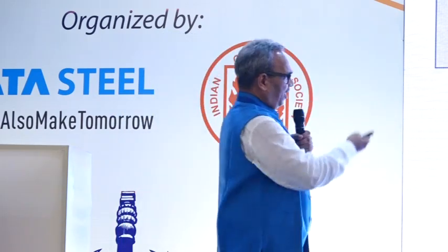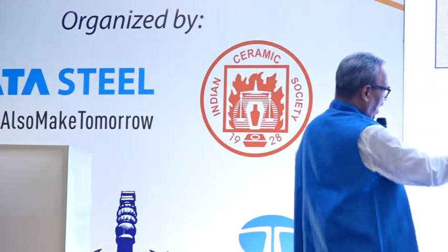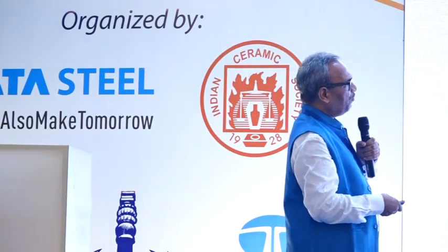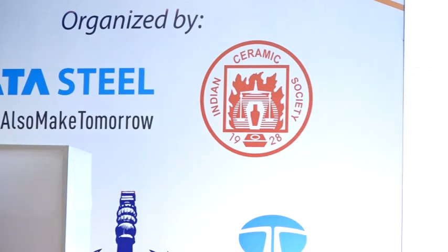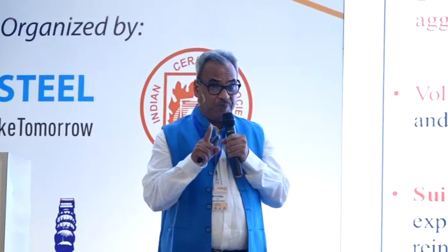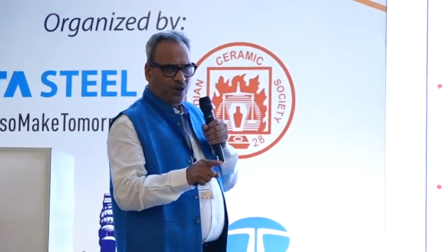So aging, we know how the aging can look like and how it can expand. And why is this? Because we can see from the LD slag graph, free lime in the sample which has been analyzed is 4.5%. So the recommendation is, as I said, the durability and the mechanical properties are good in comparison to even the conventional aggregate, but the volumetric expansion study shows that expansion in the case of LD slag fine aggregate is in excess of 3% with the aggregate which has been chosen for the study. Suitable weathering methodology can be adopted to bring it down, and to ascertain the values of maximum permissible volume expansion, further study is needed.